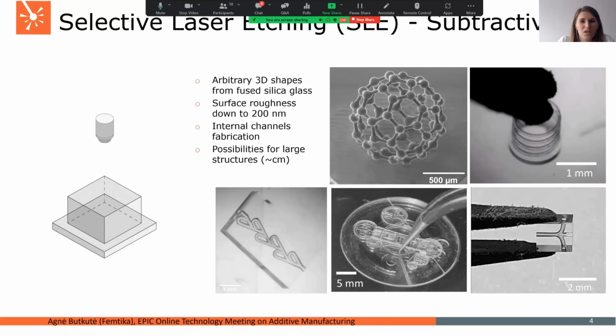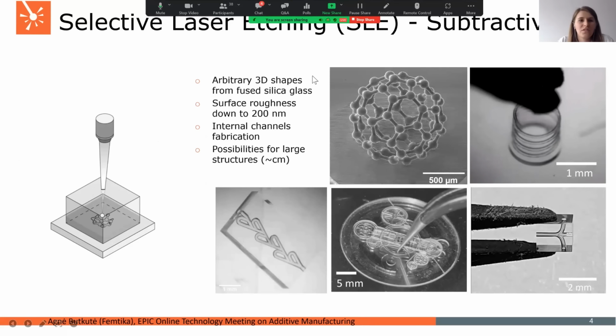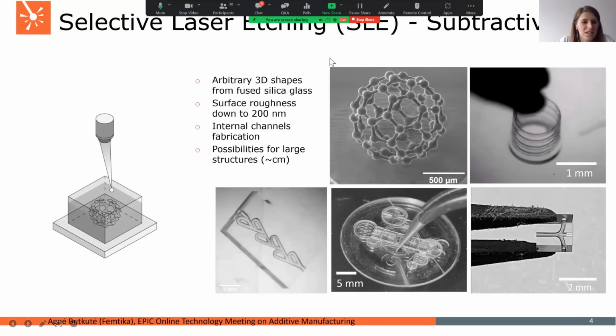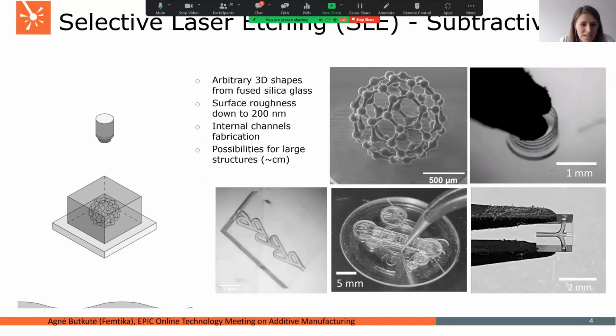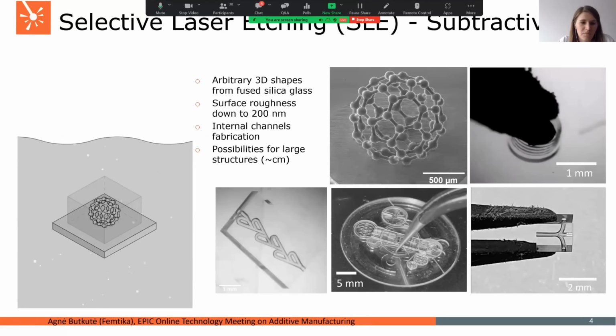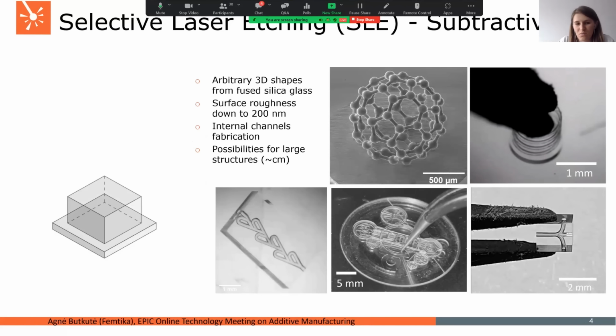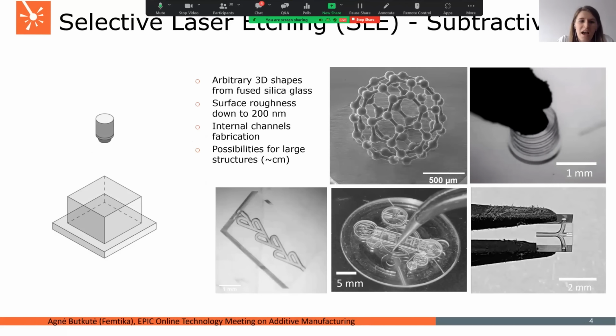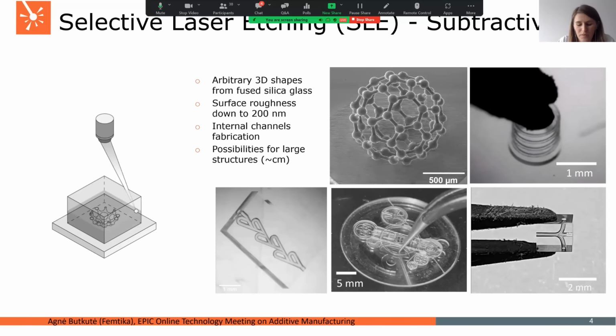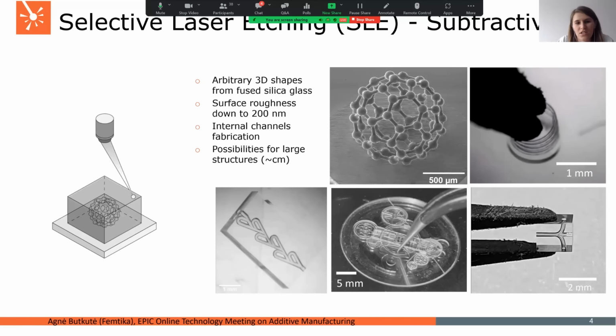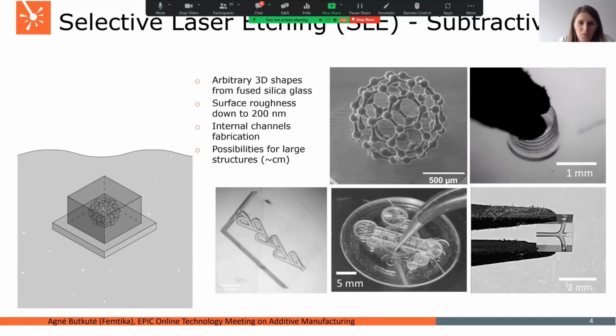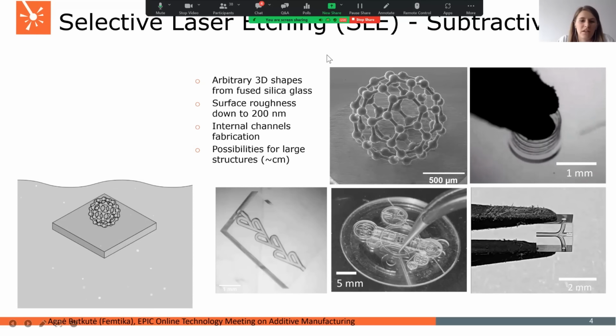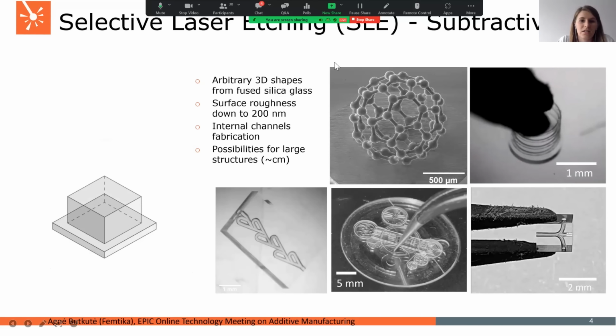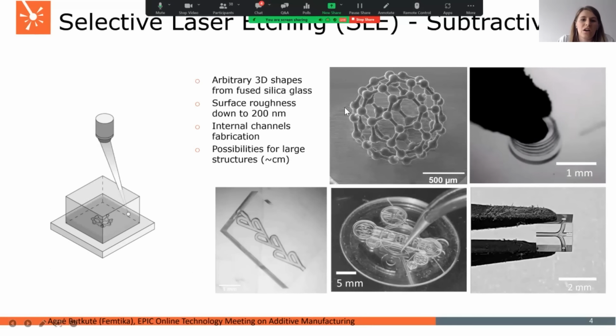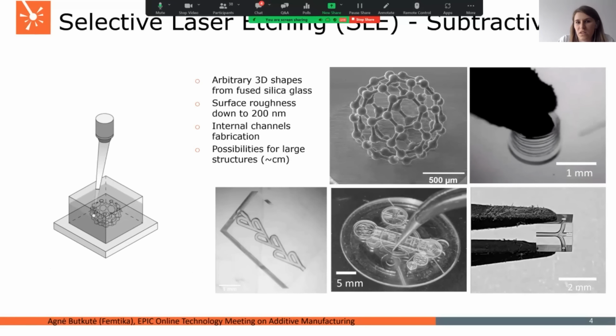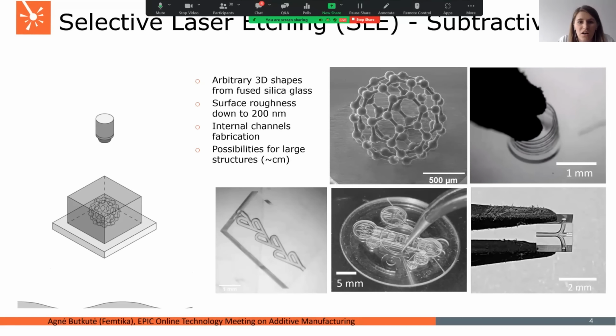Using the same system, we're also able to do a different technique, which is called selective laser etching. In this way, the process is quite similar, but we need to inscribe nanogratings inside the volume of glass, also by using a focused femtosecond laser beam. After that, those inscribed nanogratings are etched in aggressive etchants such as KOH or HF. And in that way, we can make, again, various 3D shapes in the glass. Usually, we're using fused silica glass, where the surface roughness could be down to 200 nanometers.